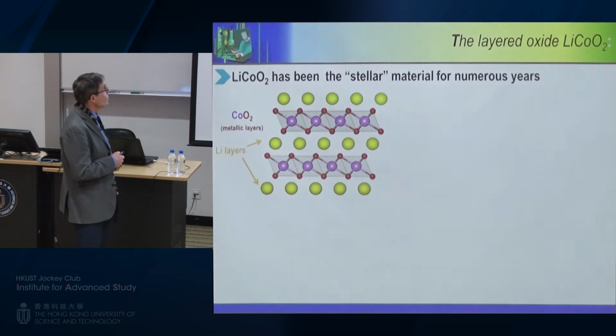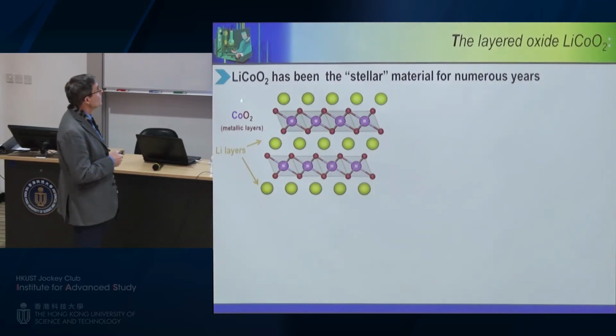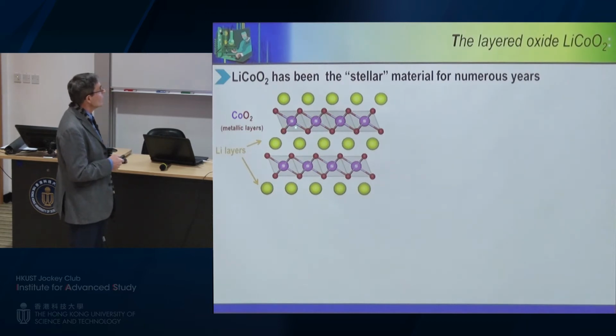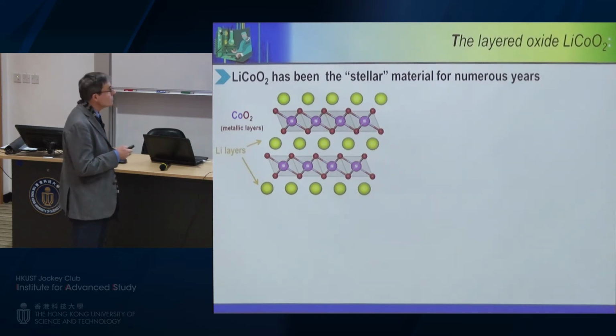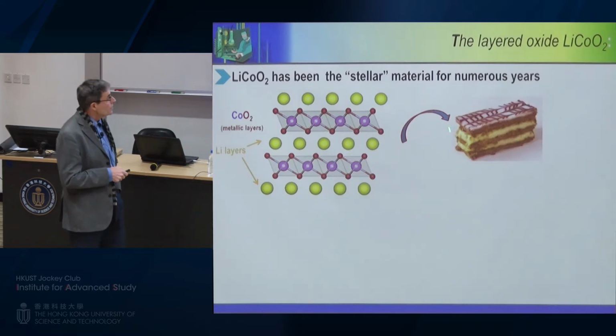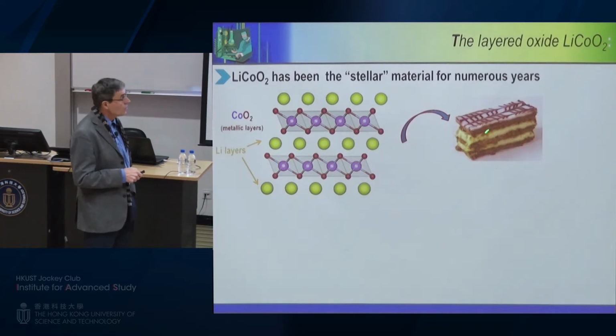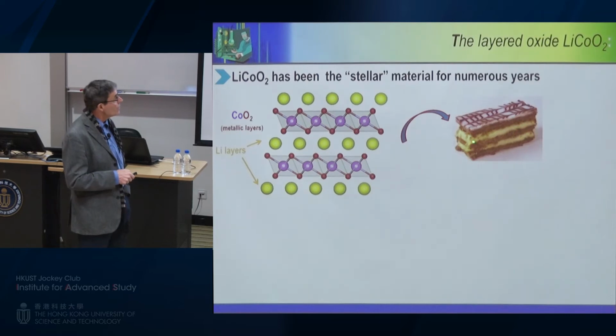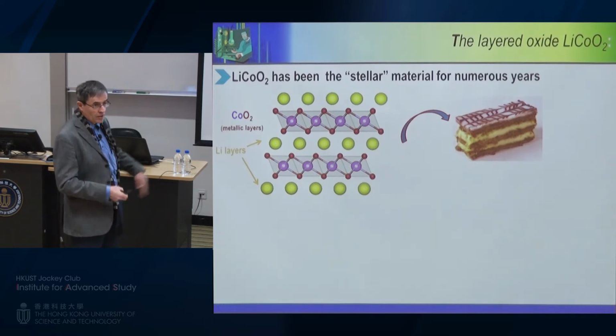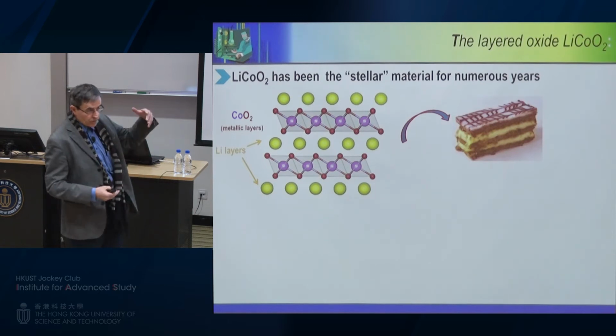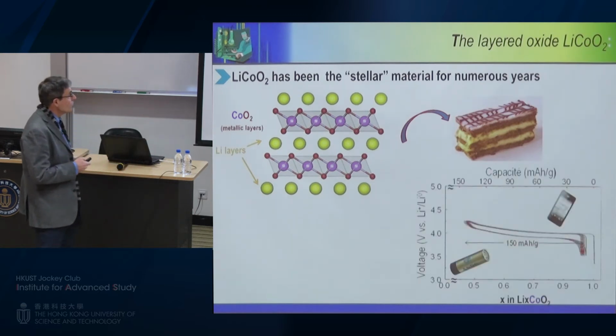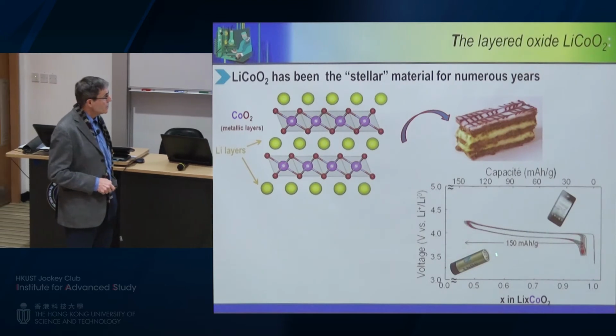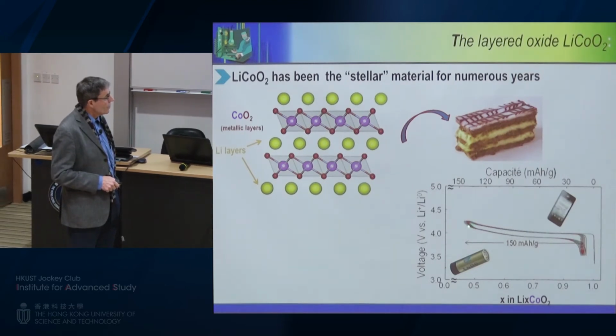So this is a type of layered oxide that all of you know, which is lithium CoO2, this layered structure, in which you have the metal layers there, and remember, these yellow atoms will be the lithium. Very simple compound. To whet your appetite, the structure is what we call in French the millefeuille, where the yellow cream is the lithium. And you squeeze, the cream is going out, and so on. So this is the material that you are using in your laptop, and as you can see here, you can charge these materials to 4.2 volts, and you get what?